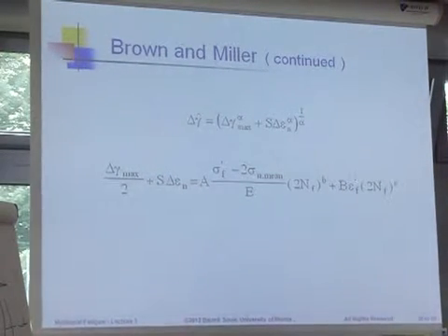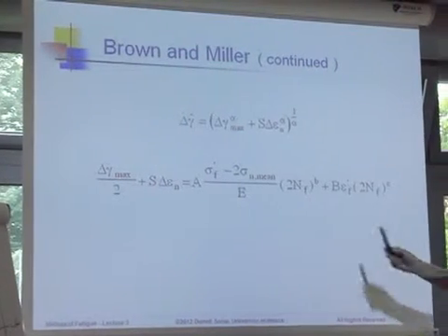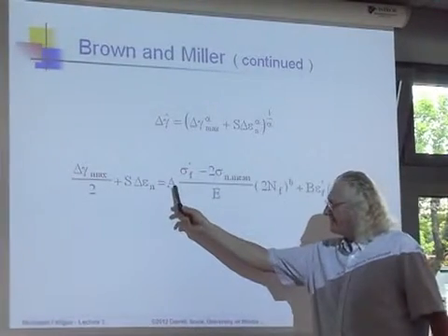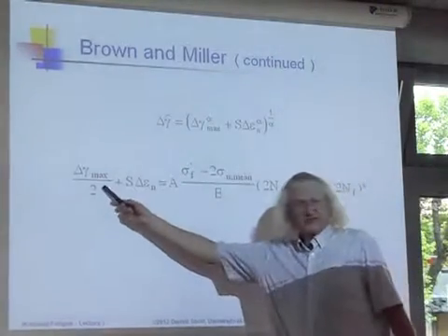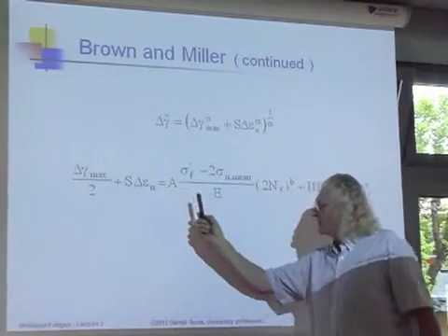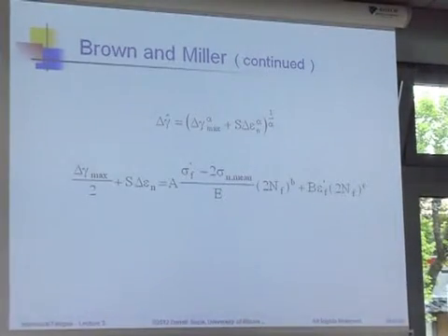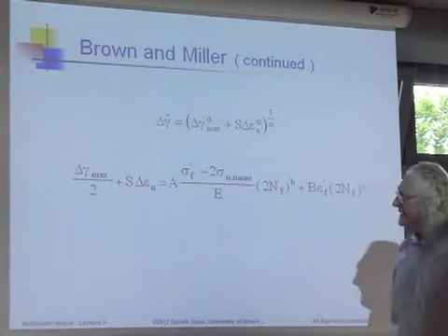They just involve Poisson's ratio, and the elastic Poisson's ratio of 0.3 and plastic Poisson's ratio of 0.5 make these constants slightly different so that you can use the shear strain here. I think this one's 1.5 and that one's 1.3, but I'm not sure of the magnitude. But I think that's what they are. And so that works pretty good.